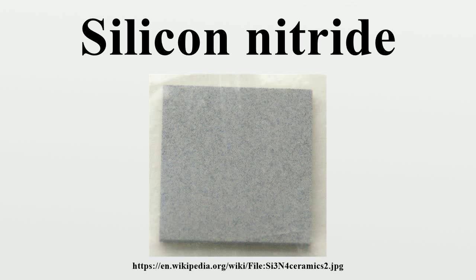In general, the main issue with applications of silicon nitride has not been technical performance, but cost. As the cost has come down, the number of production applications is accelerating. Automobile industry: One of the major applications of silicon nitride is in the automobile industry as a material for engine parts. Those include, in diesel engines: glow plugs for faster start-up, pre-combustion chambers for lower emissions, faster start-up and lower noise, and turbochargers for reduced engine lag and emissions. In spark ignition engines, silicon nitride is used for rocker arm pads for lower wear, turbochargers for lower inertia and less engine lag, and exhaust gas control valves for increased acceleration. There are an estimated more than 300,000 sintered silicon nitride turbochargers made annually.